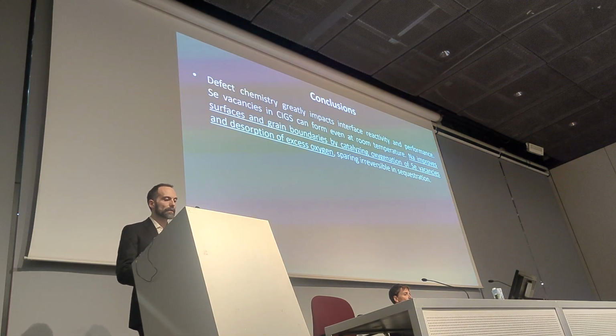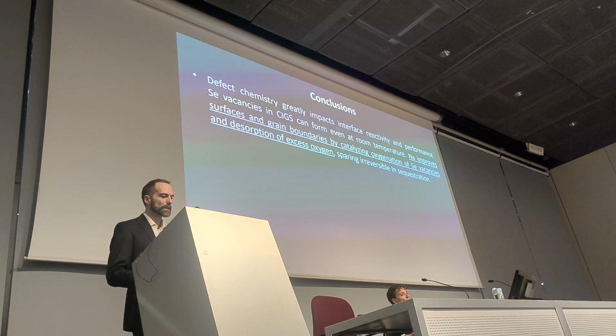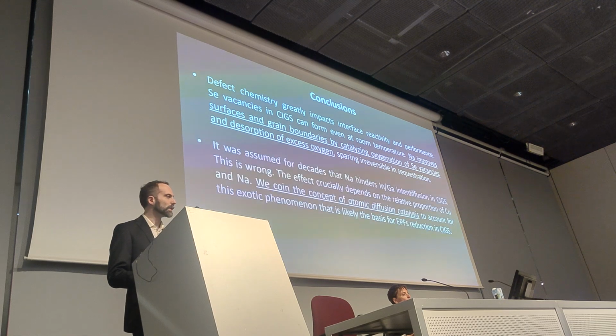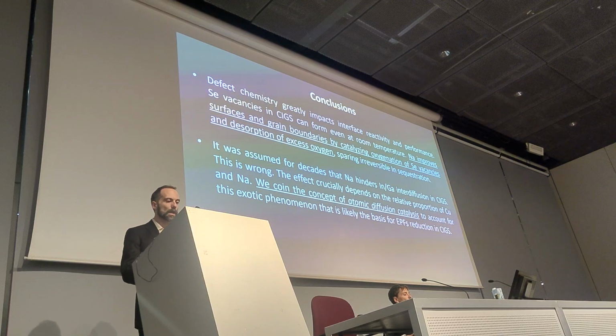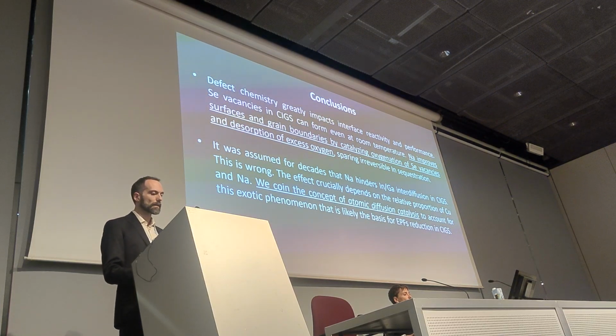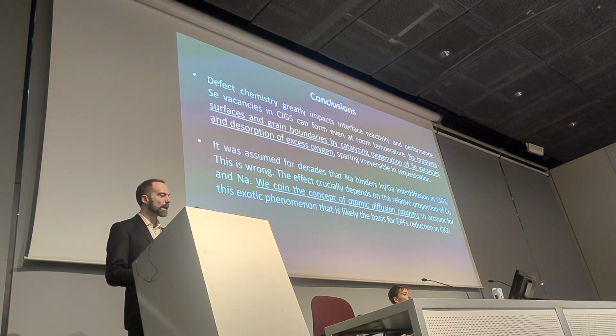So to conclude, defect chemistry greatly impacts interface reactivity and performance. Selenium vacancies in CIGS can form even at room temperature. Sodium improves surfaces and grain boundaries by catalyzing oxygenation of selenium vacancies and desorption of excess oxygen, sparing irreversible indium sequestration. It was assumed for decades that sodium hinders In/Ga interdiffusion in CIGS. This assumption is simply wrong. The effect crucially depends on the relative proportion of copper and sodium. We coin the concept of atomic diffusion catalysis to account for the exotic phenomenon that is likely at the basis of EPF's reduction in CIGS.